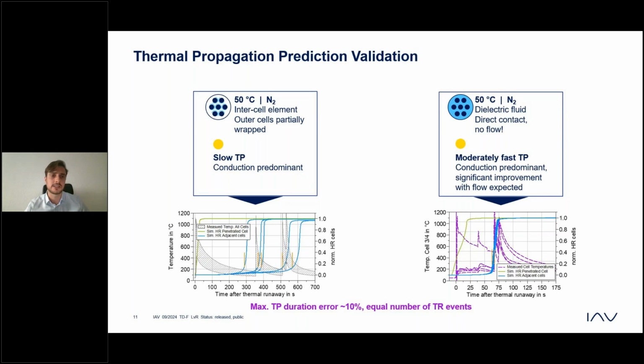And what we can see here is a similar behavior as in the experiment, where we have the first cell seeing the thermal runaway with the nail penetration, and the outer cells seeing the thermal runaway with a delay. We have marked with these orange lines the differences between the measurement and the simulation, and we come to the result that the delta T between the experiment and the simulation was a maximum of 10%. So this is a fairly good approach to see if thermal propagation is taking place or not.